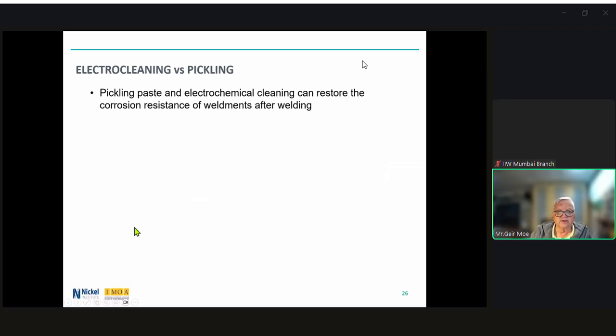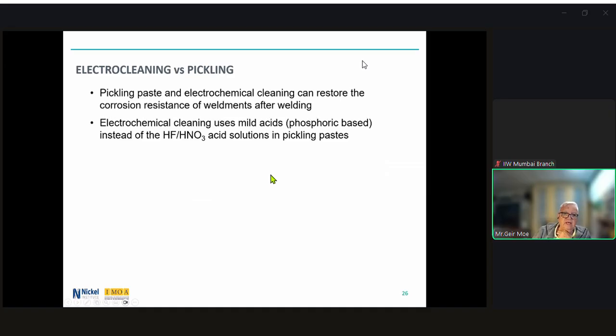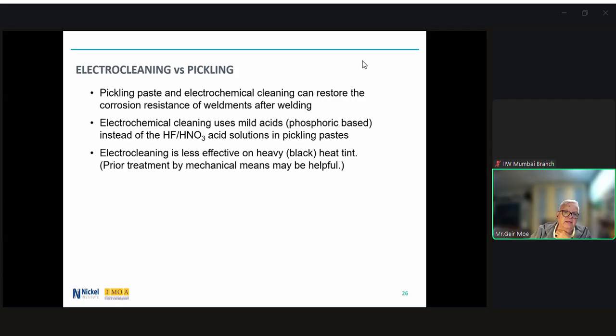So just a few comments about electrocleaning versus pickling. Pickling paste and electrochemical cleaning can restore the corrosion resistance of weldments after welding. Electrochemical cleaning uses mild acids, say possibly phosphoric acid based, instead of the hydrofluoric-nitric acid solutions in pickling paste.